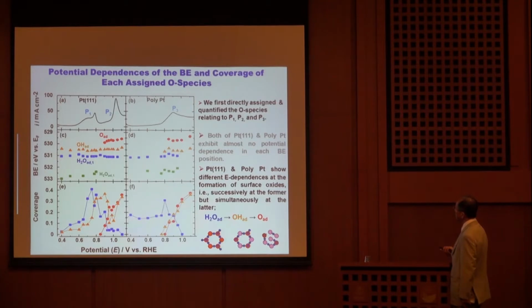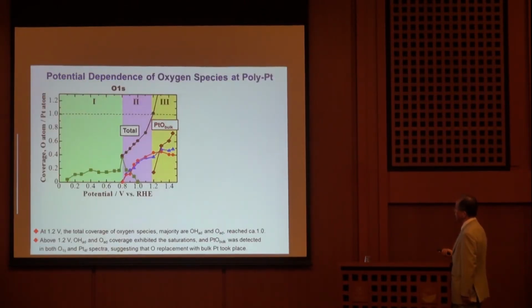Thus, we first directly assign and quantify all the species on peak 1, peak 2 on a single crystal surface, and peak 3 on a polycrystalline surface. Beyond 1.2 volt, both OH and O species level off as shown here, but in this region, another oxygen species increased, which is assigned to the bulk oxide oxygen species of the platinum.